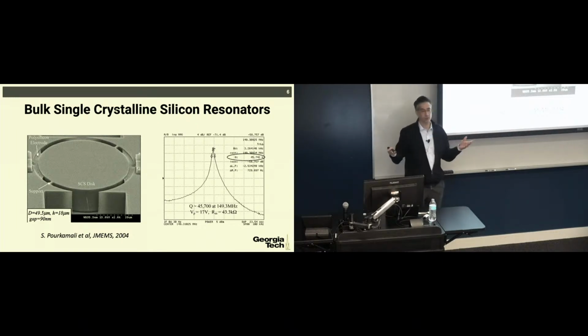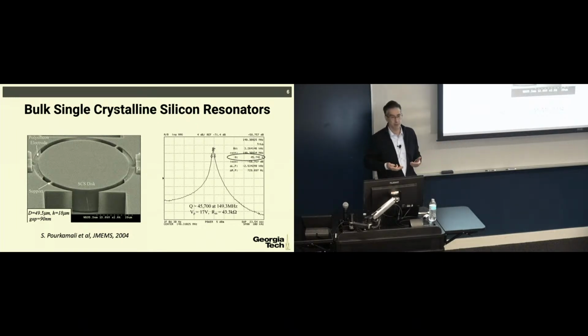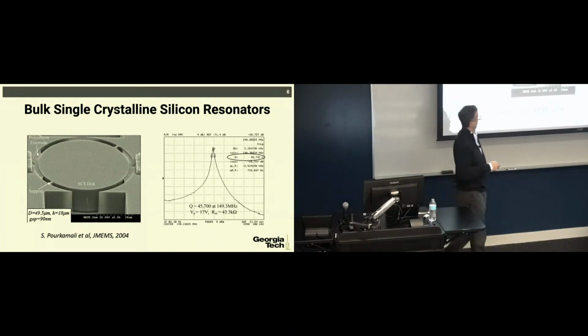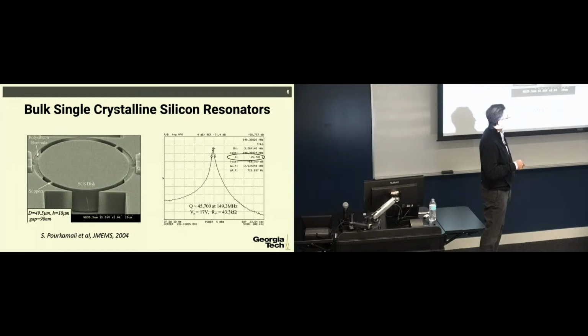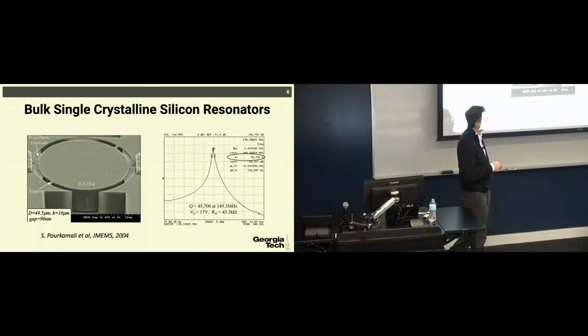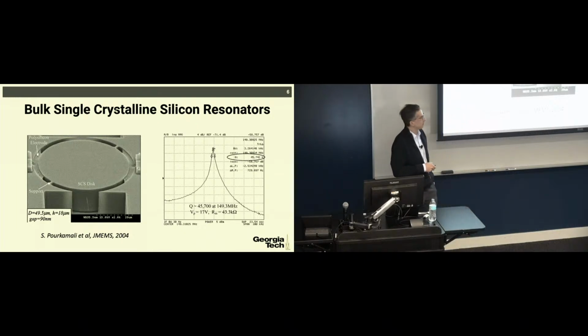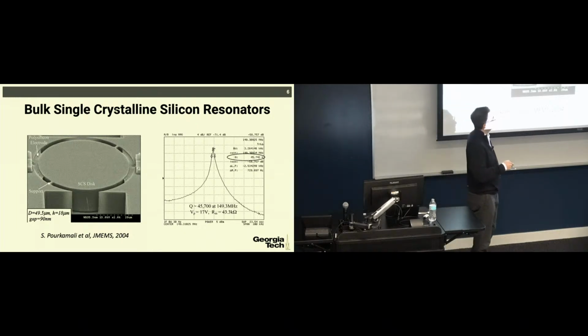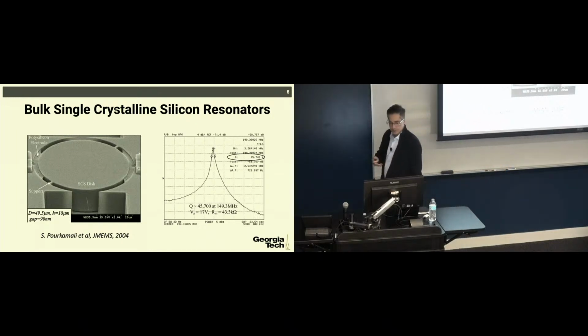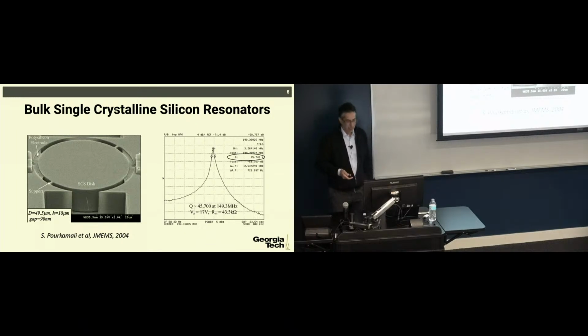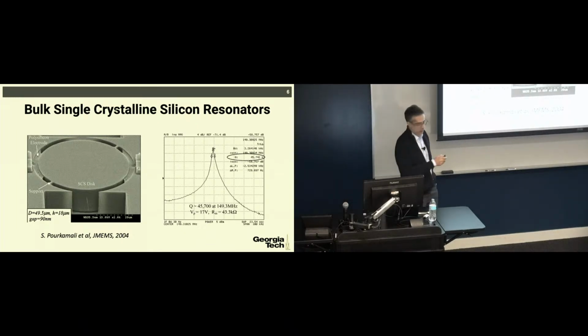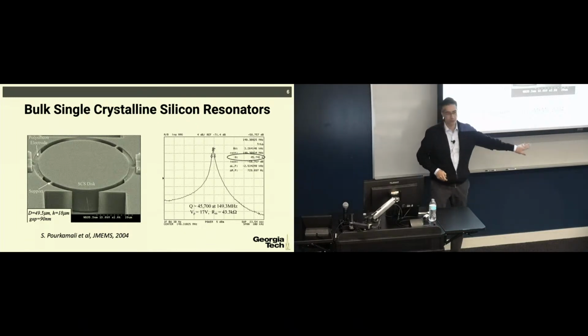electrostatically. People use piezoelectric transducers to get high-frequency elastic fields into the material. But through a lot of sleepless nights, Siavash was able to measure this Q, which was incredibly high, 46,000 at 150 megahertz from this disk resonator by applying a DC voltage to polarize the transducer. And that technology continued. This was published in journal form in 2004.